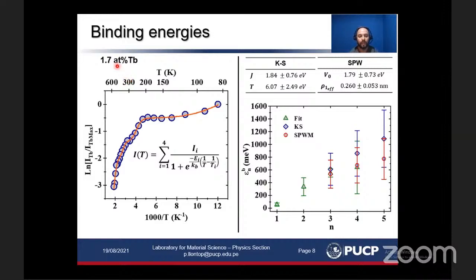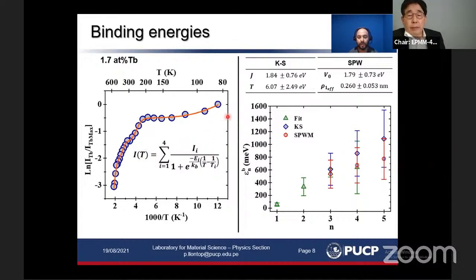Okay, anyway, so we took a sample with a slightly higher terbium concentration, and we also did the temperature dependent PL experiment, and we found this curve. So we used 4 activation energies to fit the data, and with the 2 lowest binding energies, activation energies, we calculated the parameters for both models, and these results are in good agreement with the values that we found in the literature.